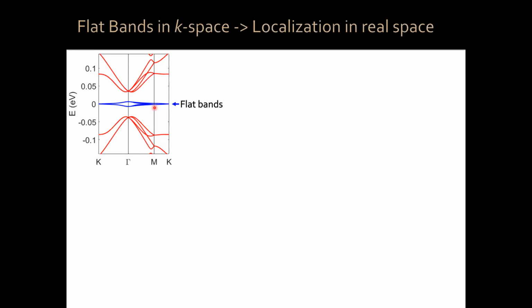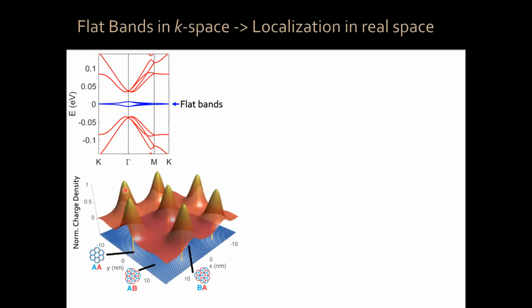So when you do the Fourier transform, you can see that the charge density, the electrons in graphene, they like to be in these regions, okay, which are locally, the two graphene sheets are on top of each other. So these regions are called AA stacking, where every carbon atom is locally on top of every carbon atom in the bottom sheet. These regions are separated by these AB and BA stacking regions, where the lattices are, because it's a small twist angle, locally shifted with respect to each other, okay?